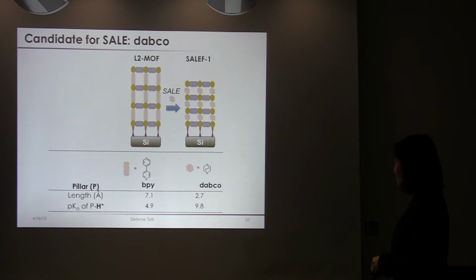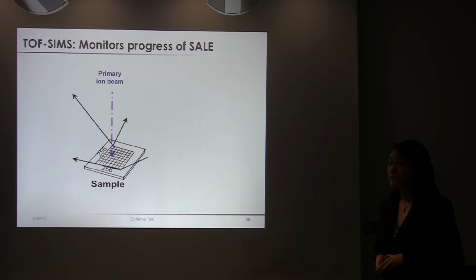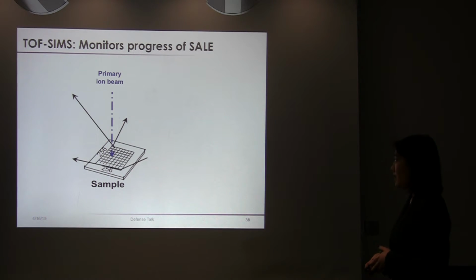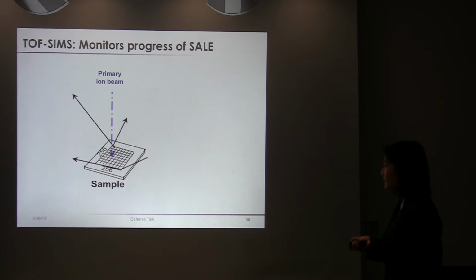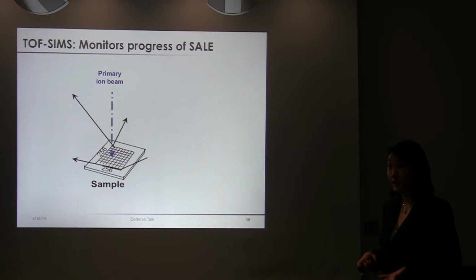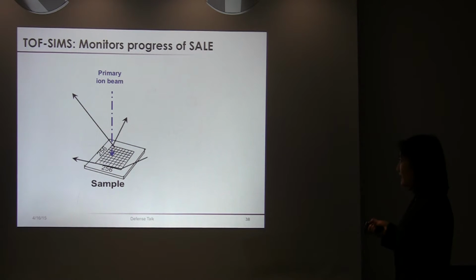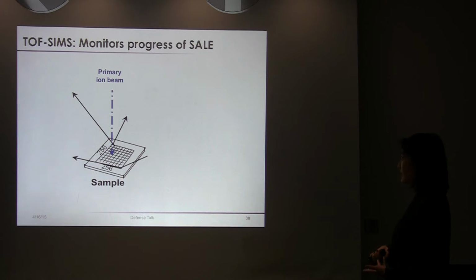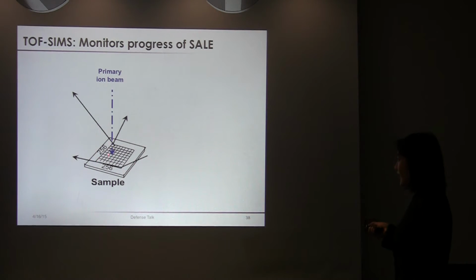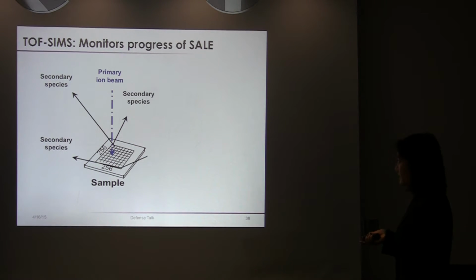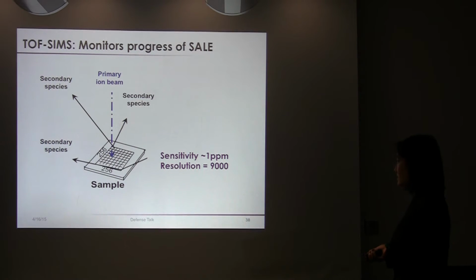Okay. So let's move ahead. All right. So typically for bulk samples of MOFs, we use proton NMR to monitor the progress of SALE. And the material quantities that are available in the thin film sample are much lower than is detectable by NMR. So I had to go around that and try to figure out what other techniques can be used to monitor the progress of SALE. And so I came up with using TOF-SIMS, or time-of-flight secondary ion mass spectrometry. This technique can be used to monitor the progress of SALE because it relies upon a primary ion beam that bombards the surface of the sample and ejects fragments or secondary species that are detected by the mass spectrometer. The main advantage of this technique is that the sensitivity goes down to 1 ppm and its resolution goes up to 9,000.